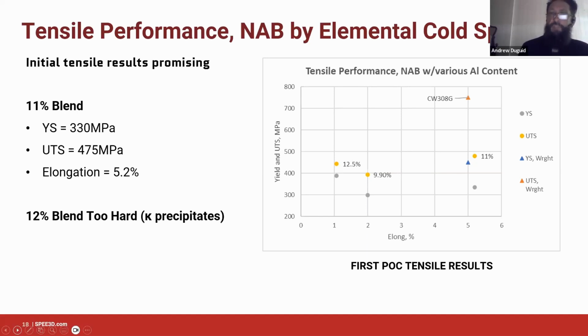What we do to visualize our tensile data is that we take the yield and UTS values from a set of tensile tests. Typically we do between 3 and 5, mostly 5. And we average those, we get an average yield and an average UTS. And we plot both of those figures against the strain to failure, which is what you can see on the two axes there: strain to failure, and the yield and UTS. And what that allows us to visualize is how ductile the alloy is, and independent of that, how hard it is in terms of its yield strength.